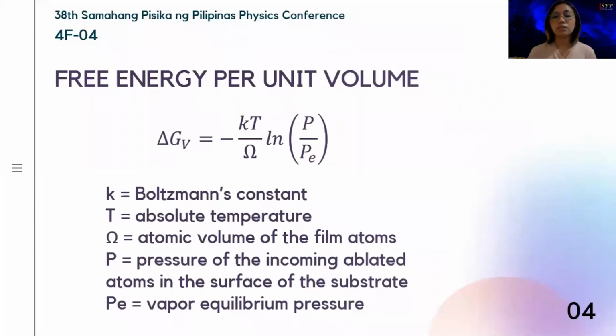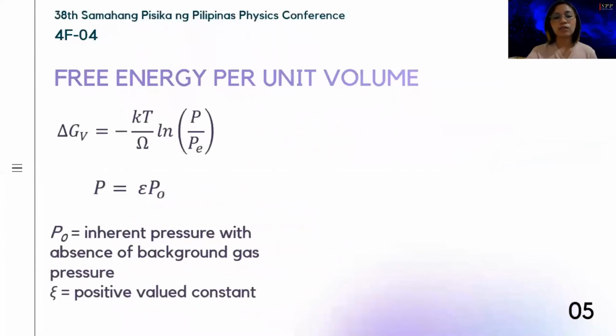The growth behavior of deposited materials in many physical vapor deposition systems can be determined using the free energy per unit volume of the vapor, or delta G sub V, given by the equation, where k is the Boltzmann constant, T is the absolute temperature, omega is the atomic volume of the film atoms, P is the pressure of the incoming ablated atoms, and P sub e is the vapor equilibrium pressure. To relate delta G to the background gas pressure, we set P equal to epsilon P naught, where P naught is the inherent pressure in the absence of any background gas, and epsilon is a positive valued constant that relates the background gas pressure P to P naught.